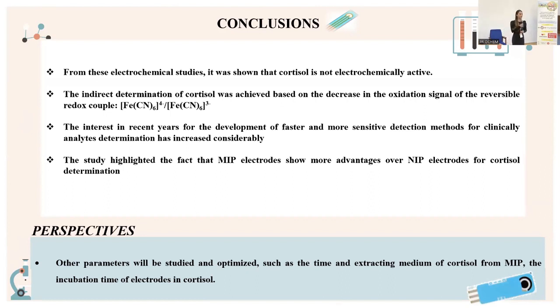In conclusion, from this electrochemical study, it was shown that cortisol doesn't have electrochemical activity, but the indirect determination of this compound was realized with success using the redox couple ferrocyanide. On the other hand, the study highlighted the fact that molecular imprinted polymer electrodes have a lot of advantages in using them in detection, and the interest for the development of faster and more sensitive detection methods for clinically analyzed compounds, in this case the cortisol, has increased considerably in last years.